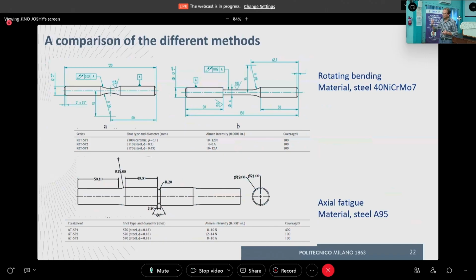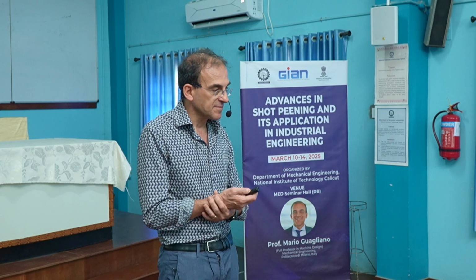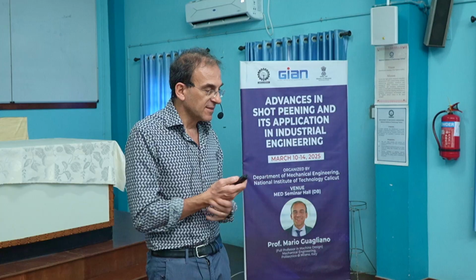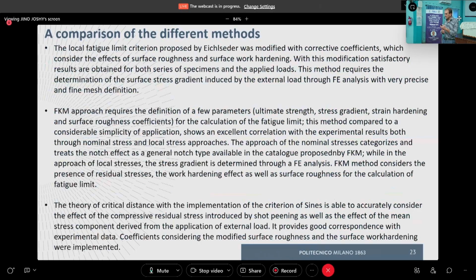And then we ran this test on this specimen, and we applied the different methods to the same experimental result to see, at least for this geometry, which is the criterion that gives the most accurate result. Okay, and to cut the long story short, let's see which comments we can make.